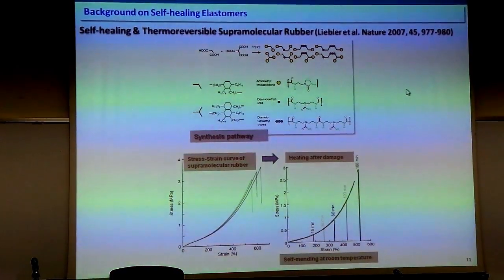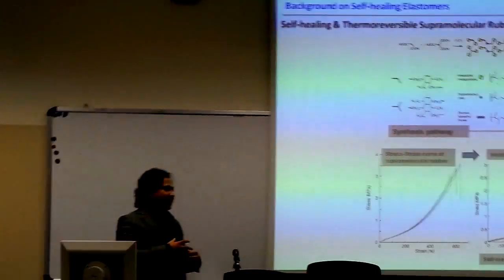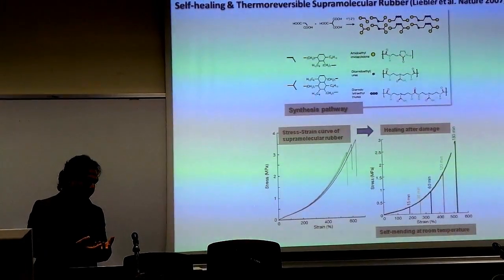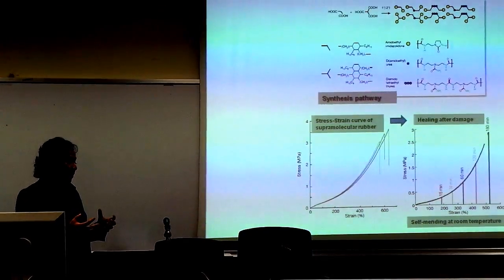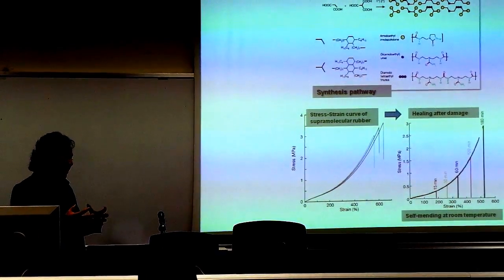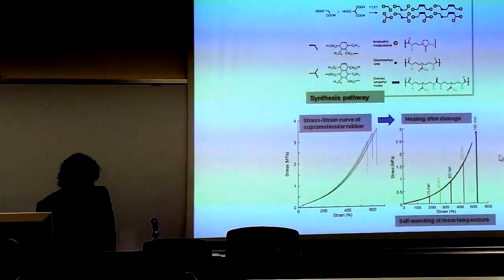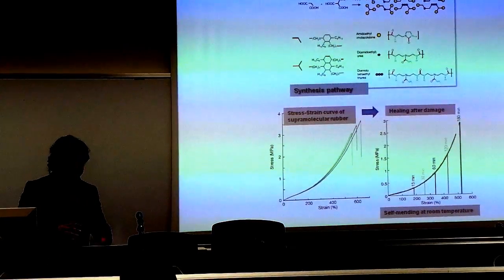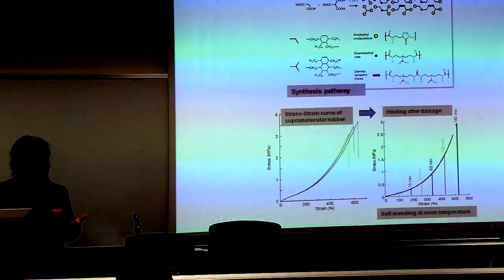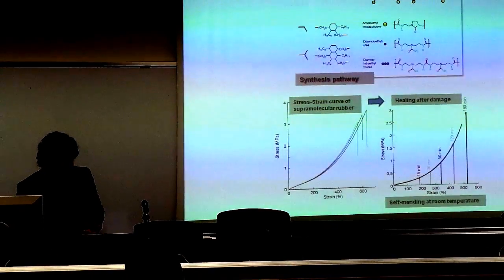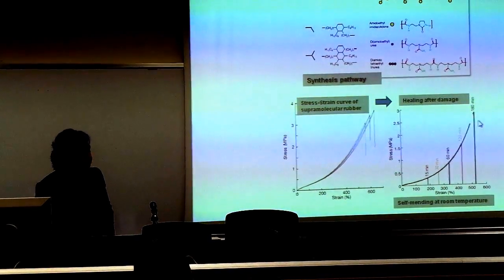And he actually developed a dynamic supramolecular approach to synthesize the supramolecular self-healing rubber, where it contains multivalent hydrogen bonding, which are individually weak but collectively can have a high load bearing capacity, as you can see in the stress strain curve of this pure rubber. And they studied the self-healing behavior by cutting the sample in the middle and then putting it together just by pushing by hand. And after 180 minutes, the sample showed 90% recovery of its pulling strength.